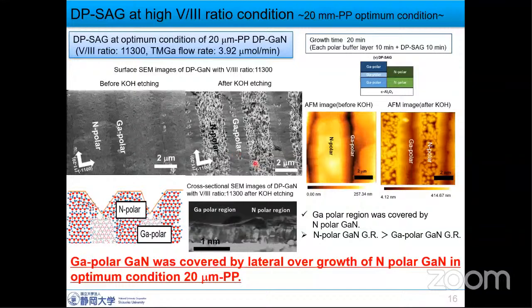As you can see, the AFM image before KOH etching shows that the gallium polar region was covered by nitrogen polar gallium nitride lateral overgrowth. And the AFM image after KOH etching shows that the nitrogen polar region was etched. This sample schematic image is shown here.